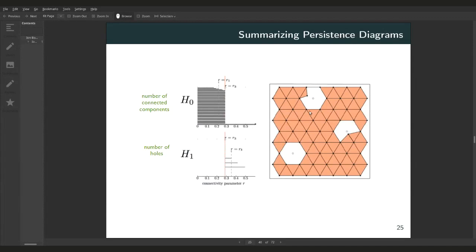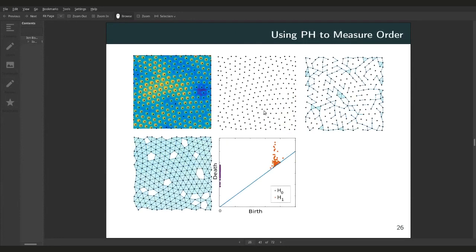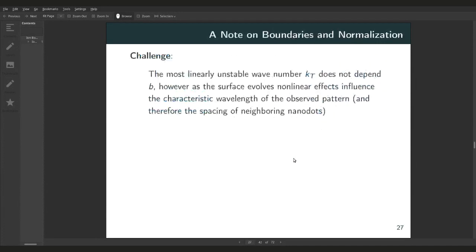Here we can see several defects. This is one example of a threshold value and the Vietoris-Rips complex associated. We're missing a peak, and we have several perturbed points. Those appear as H1 bars, and they also cause some variance in some of the H0 bars. Okay, so we can apply this to real data. I have the peak locations and several different threshold values, and all of this variance and all of this spread are indicators of defects in the system.